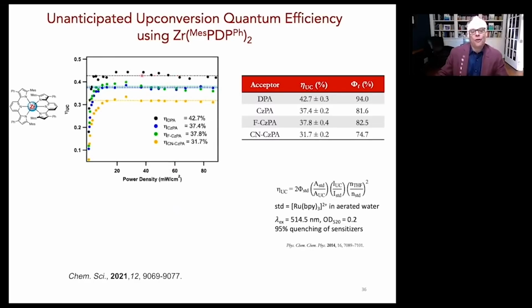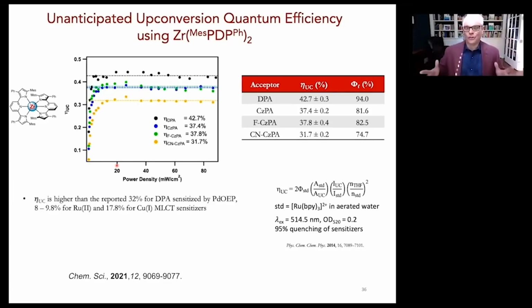And then, of course, all of the plots wind up giving you normalized upconversion efficiencies. The highest one that we can measure is 42.7%, which is the average right through here. But we believe that's simply reflecting 40% within our experimental error. And 40% is really the maximum you can get from diphenylanthracene, in our opinion. So this sensitizer got us to the maximum at a power density that's actually lower than if you integrate the absorption band over the entire solar spectrum range. It's actually less than 19 milliwatts. So we think we can actually run this particular upconversion with sunlight at one sun at the highest possible efficiency, which is quite amazing to us.